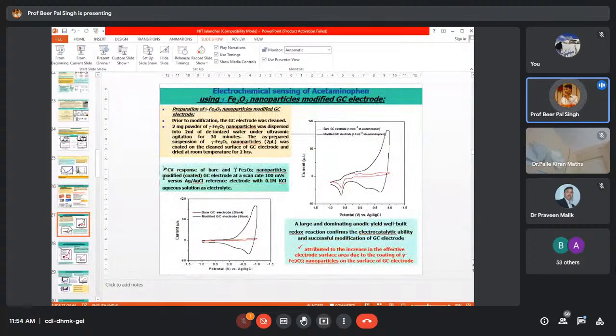And in this slide, I have shown that we have used the gamma phase of iron oxide nanoparticles to sense this drug acetaminophen, or Calpol or Dolo. And the thing is that in our three-electrode cell, we modified the glassy carbon electrode, which was the working electrode, with our iron oxide nanoparticles. And then we went for CV measurement of this experiment. In that case, you are seeing the CV measurement of bare glassy carbon electrode as well as modified glassy carbon electrode without acetaminophen.